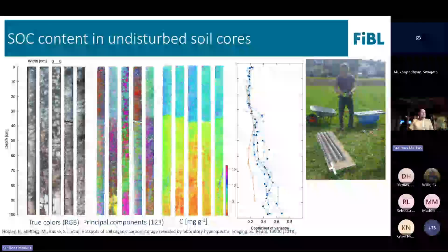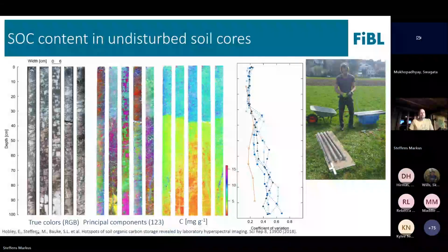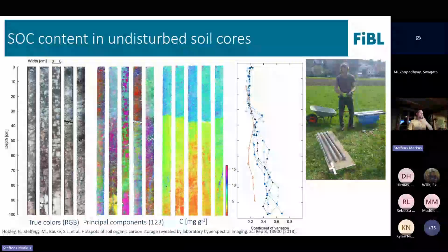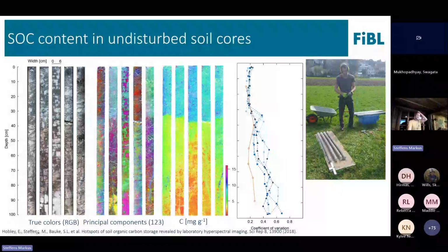And then you see some intermediate results. So these are principal component analysis. So these are the next 5 colorful pictures. Basically, it's just showing where you see differences, where there are different materials. And then the last 5 that you see here, this is the carbon map. And we again see quite nicely the AP, so the plowed topsoil horizon, which is rich in carbon, which is the blue here. And then you see this very sharp edge where you have the plow pan, or where the plowing stopped, and then you have less carbon.